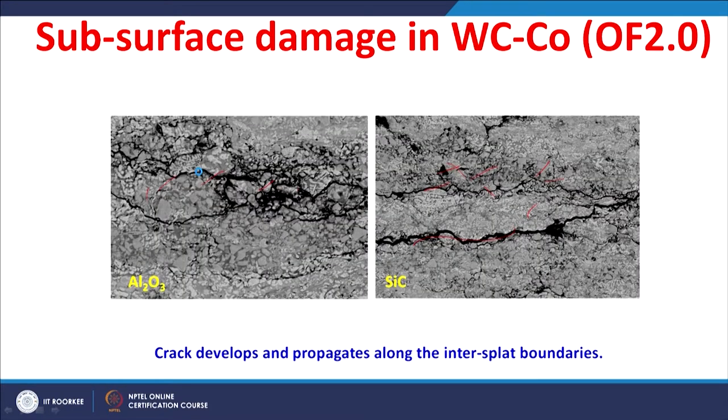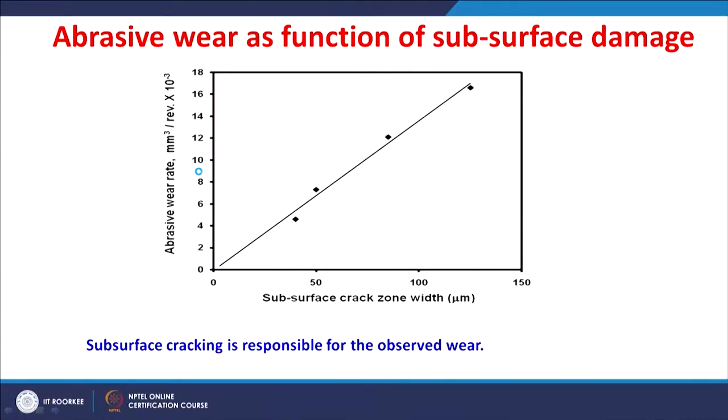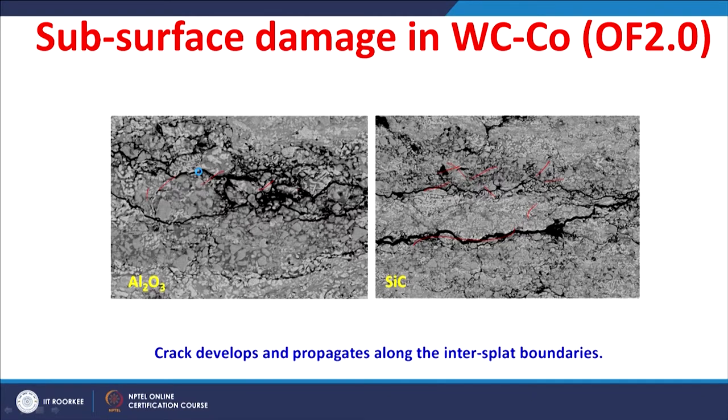So these subsurface cracks and the resultant damage can also be understood with respect to the subsurface crack zone width and the abrasion wear rate behavior. Here the abrasion wear rate is plotted as a function of subsurface crack zone width. We found the subsurface cracks are dominant in the case of the tungsten carbide cobalt coating done with the oxygen to fuel ratio of 2.0